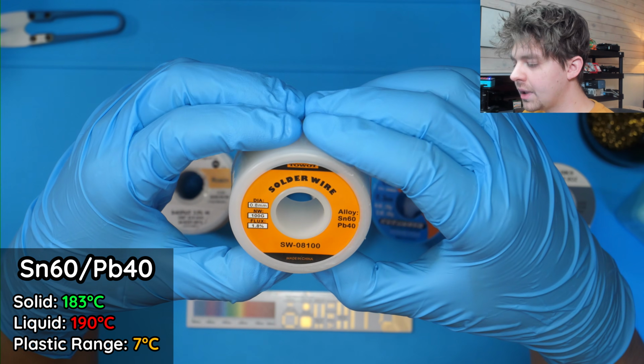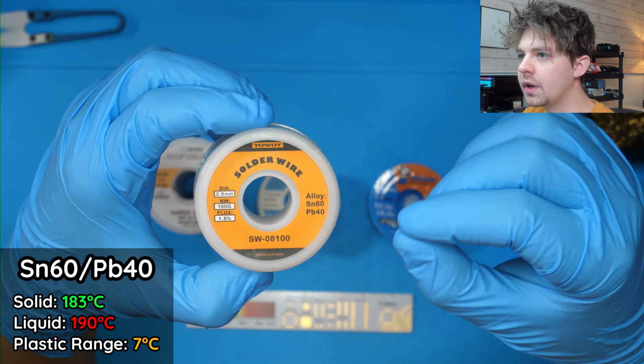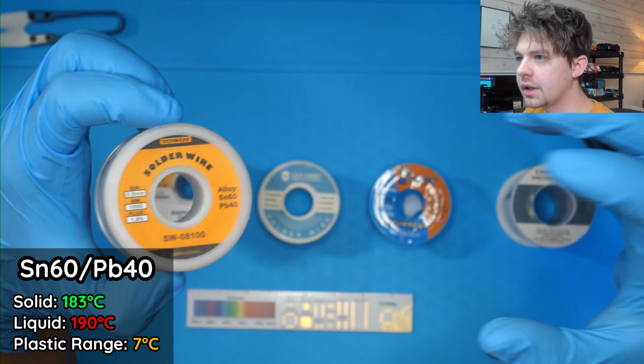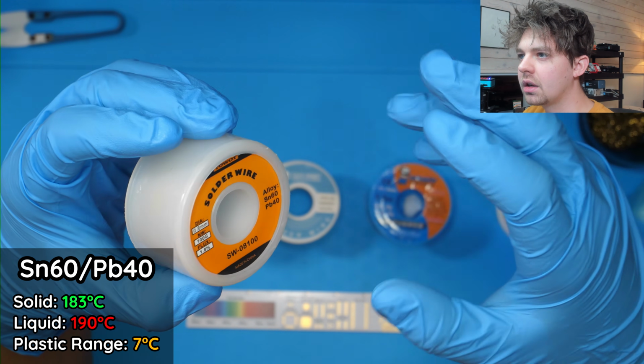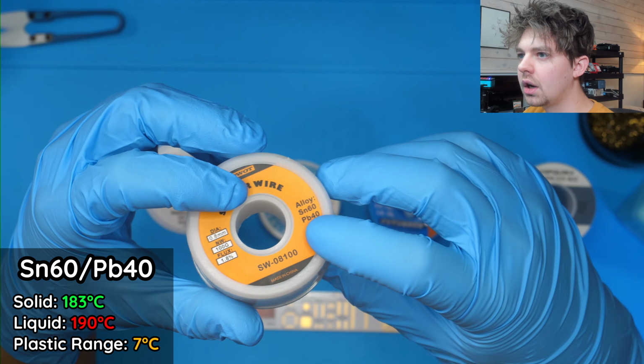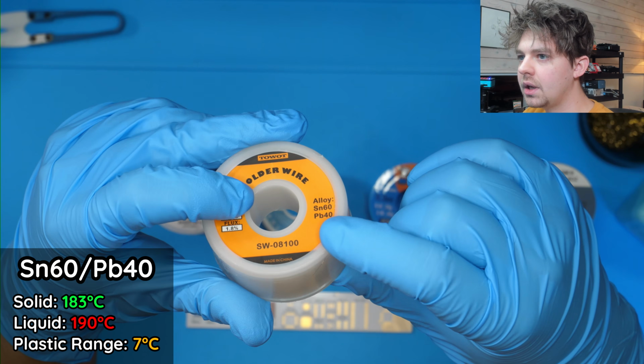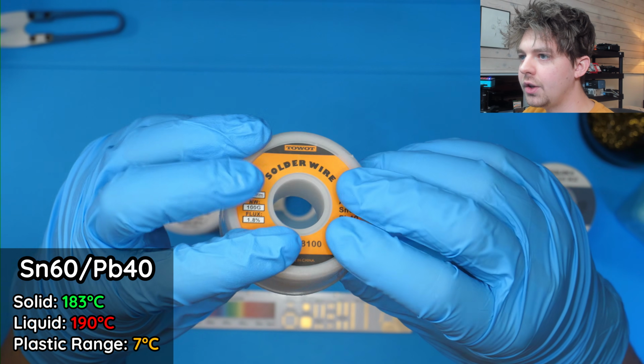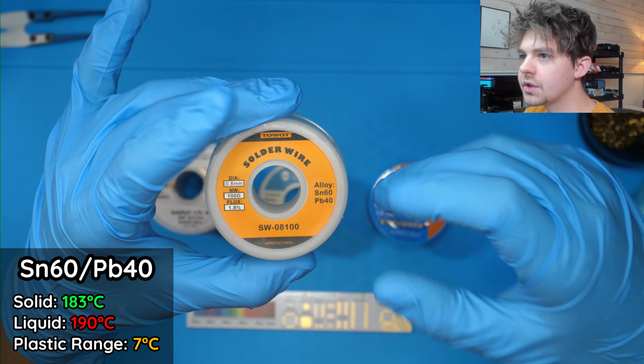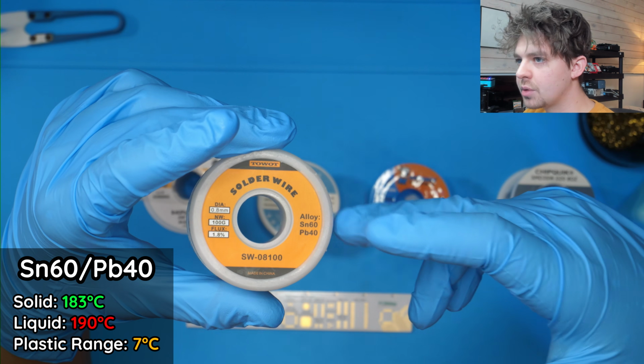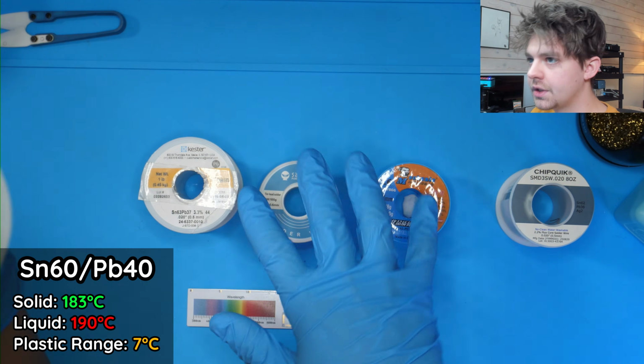When we use it on the board, because of that plastic state, if you end up moving the components around while they're solidifying, it's going to make for an ugly, gray, dull color of the solder, and it's going to be a weaker solder joint than you get if you were to hold it completely still. So it's easier, in my opinion, to make poor joints with this stuff versus the eutectic stuff.